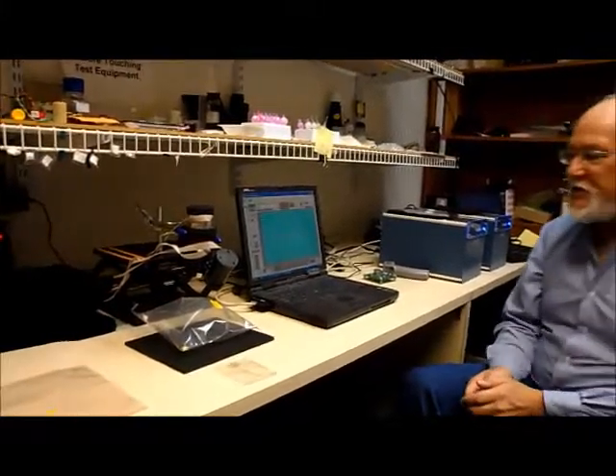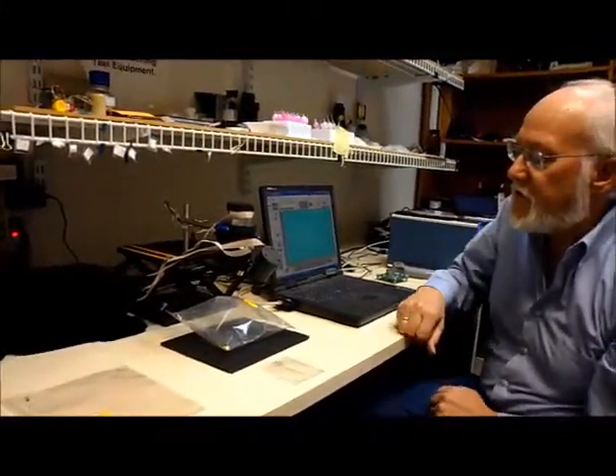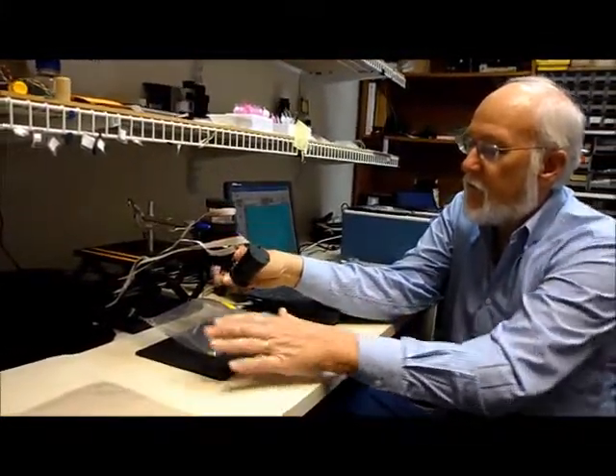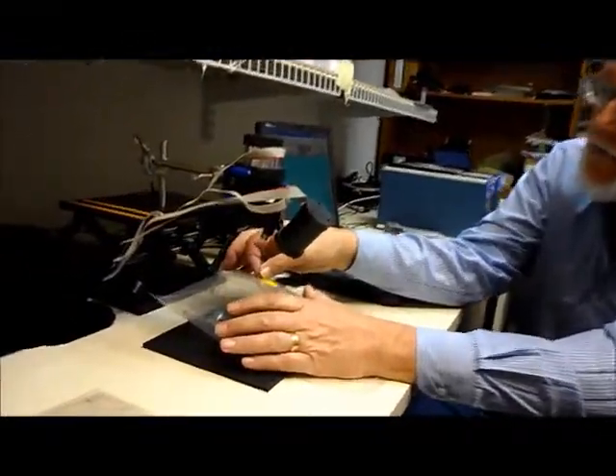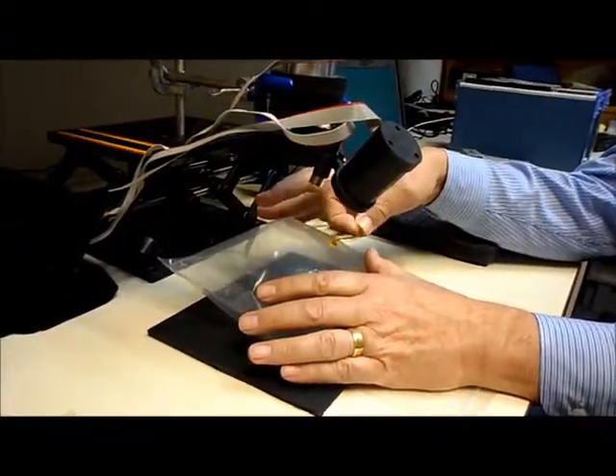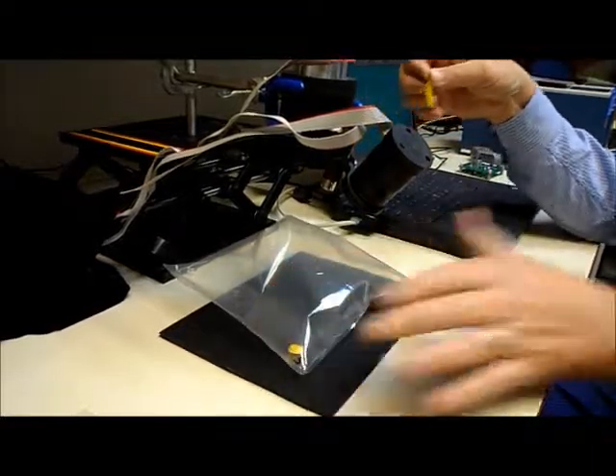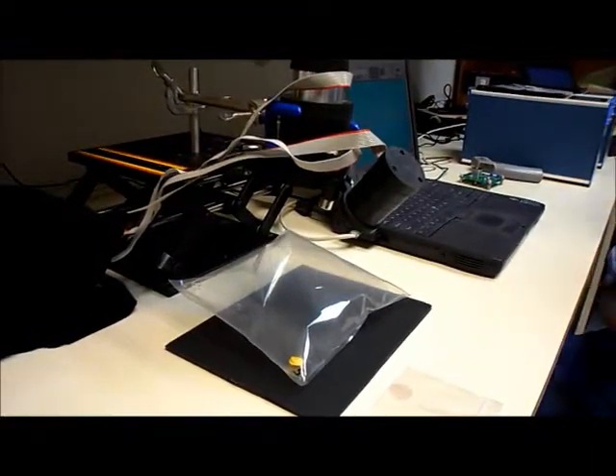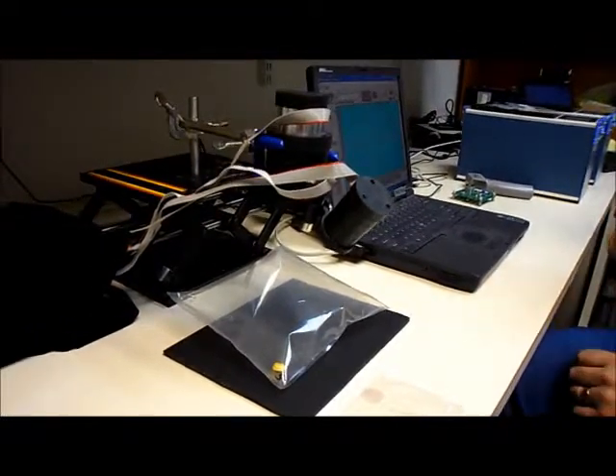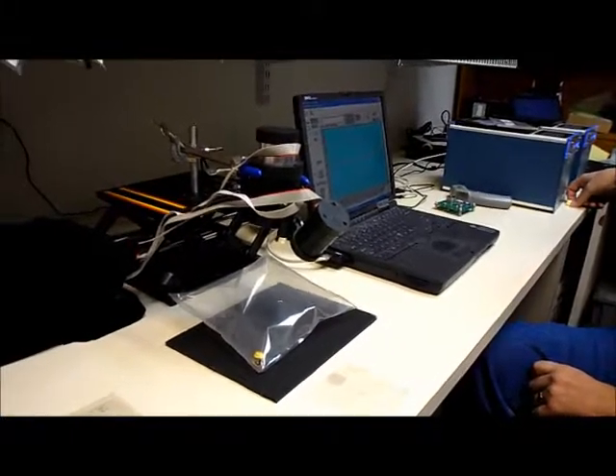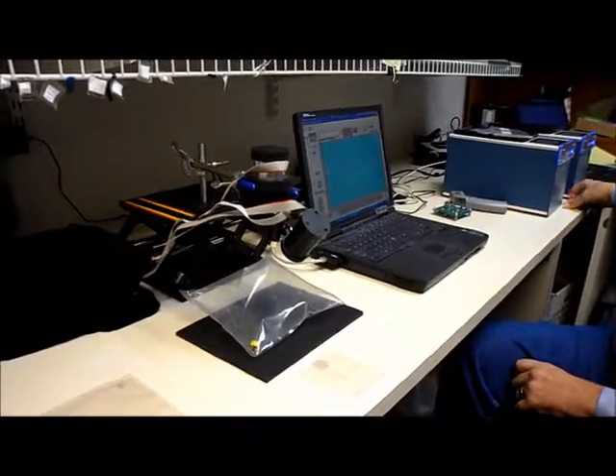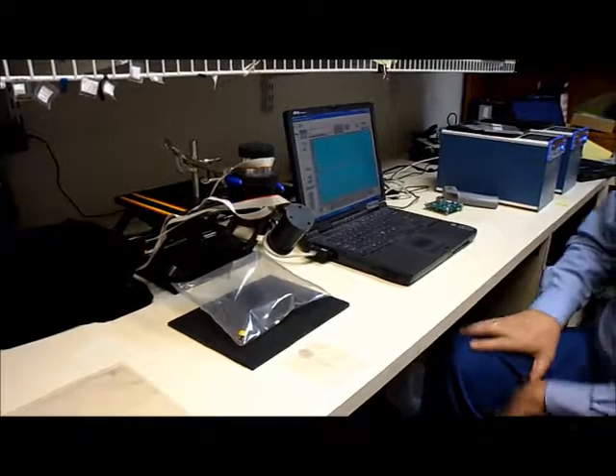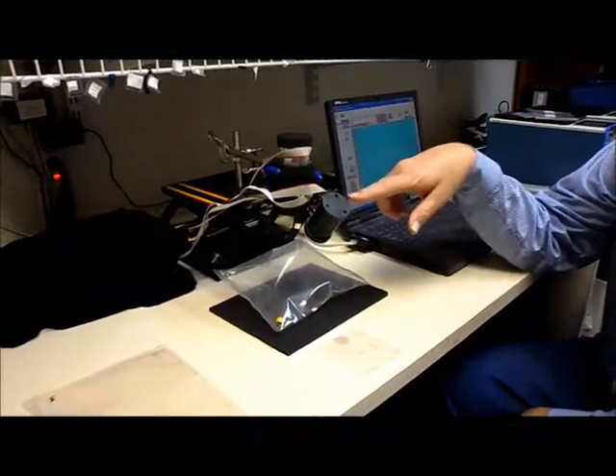What the system consists of, well, what I'm going to do first is I'm going to take and remove the tape that's covering the hole on the bag, and that's where the nitrogen was injected into the bag. We'll just let it sit there and leave it for a couple of minutes, and we'll look at the change then as measured by our oxygen sensing system.